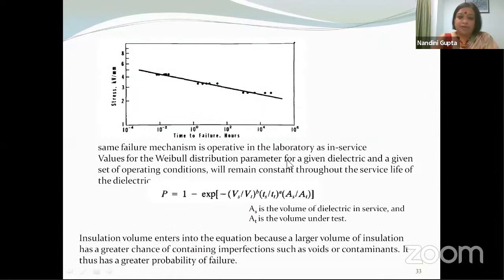So values for Weibull distribution parameters for a given dielectric and a given set of operating conditions will remain constant throughout the service life of the dielectric. And from this expression, you can obtain the life of the insulation. It depends upon the service voltage, test voltage, service time, test time. It also depends upon the volume of the dielectric in service and the volume under test. Obviously, the volume under test is going to be much less than the volume under service, and you have to